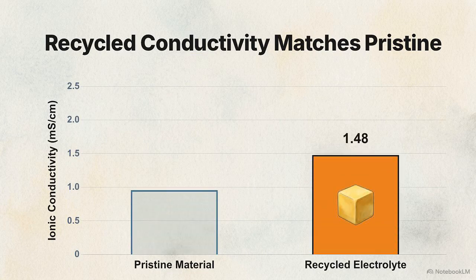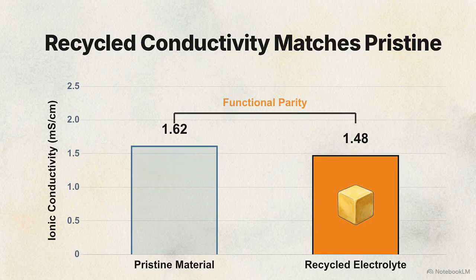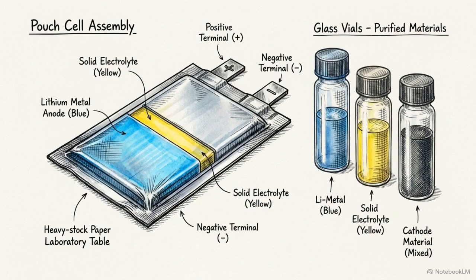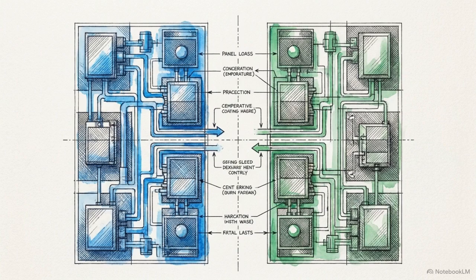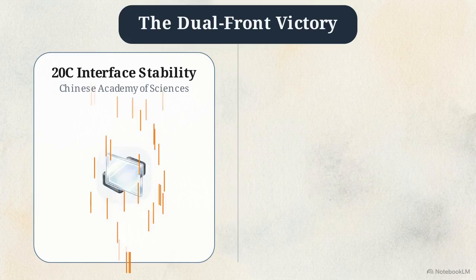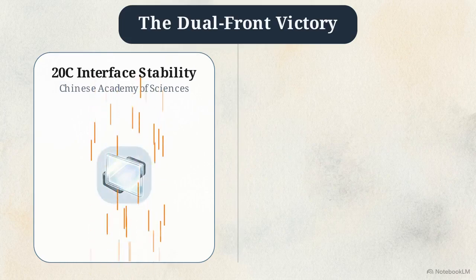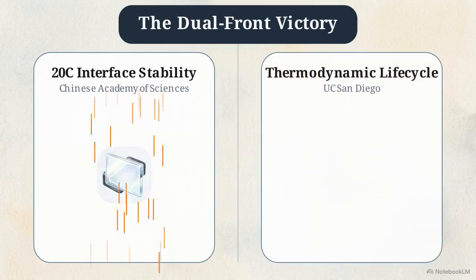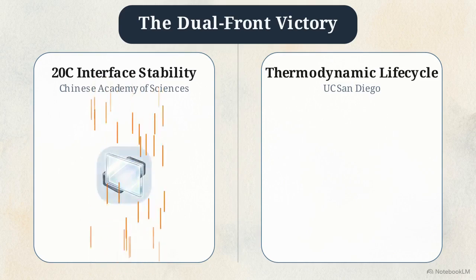The recycled solid electrolyte returns an ionic conductivity of 1.48 millisiemens per centimeter. It operates in the exact same order of magnitude as the 1.62 millisiemens measured in the pristine material. We do not have to sacrifice energy density or conductivity metrics to achieve closed-loop material sustainability. The solid-state storage roadmap relies on two parallel engineering tracks: the 20C interface stability, demonstrated by the Chinese Academy of Sciences, and the thermodynamic life cycle framework modeled by UC San Diego.